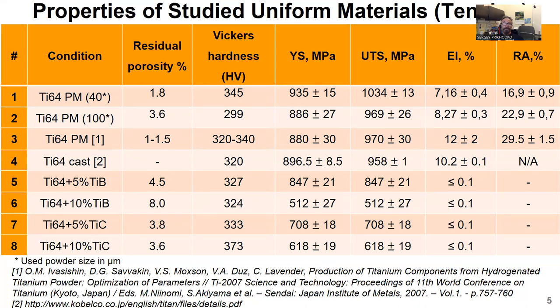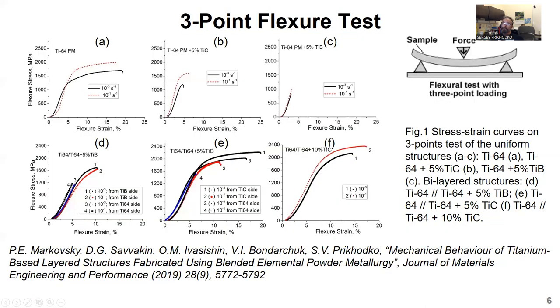We see some increase in Vickers hardness. However, the yield strength and ultimate tensile stress of the composite are substantially lower than those of sintered alloy, as well as cast and wrought, shown here for comparison. So overall, it doesn't look like a very encouraging result to begin with.